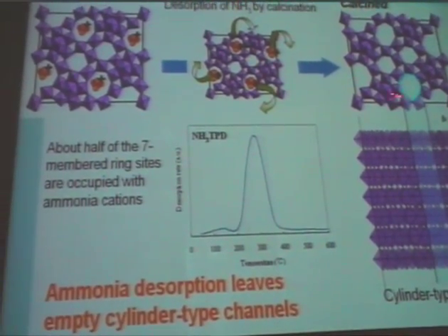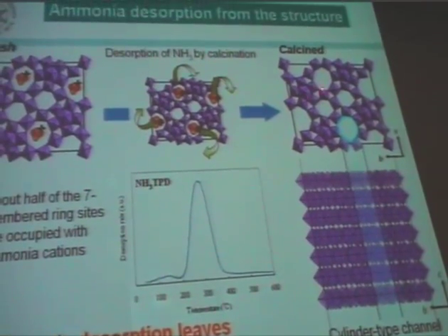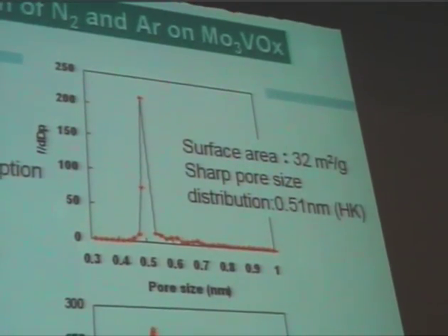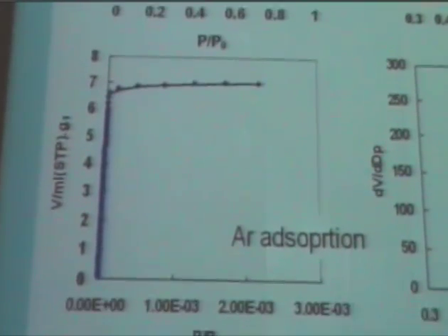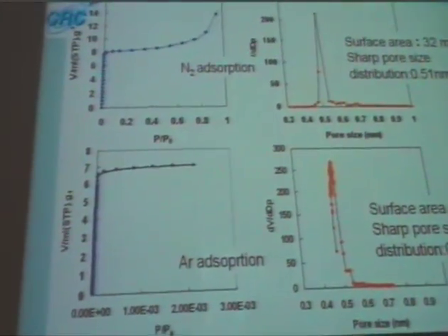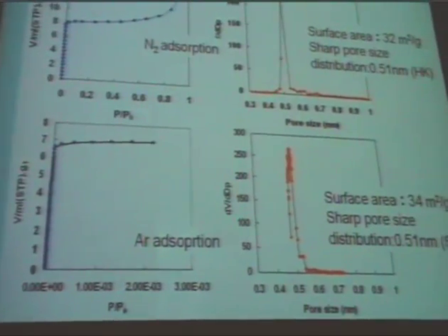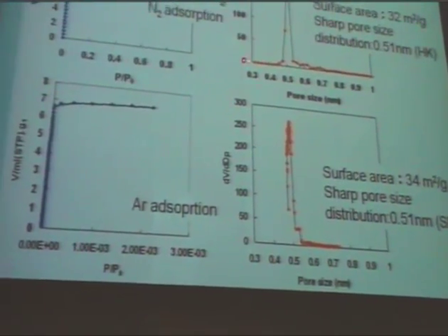There is nothing in the pore after heating — there may be something in there but it's not easy to identify. Anyway, you can get these porous samples. Then we measured the nitrogen adsorption and argon adsorption at low temperature. We observed very sharp adsorption at very low relative pressures of nitrogen and argon. Based on this adsorption isotherm, we calculated the pore-size distributions, giving a 0.5 nanometer size pore, which is uniform, with no other pore-size distributions.